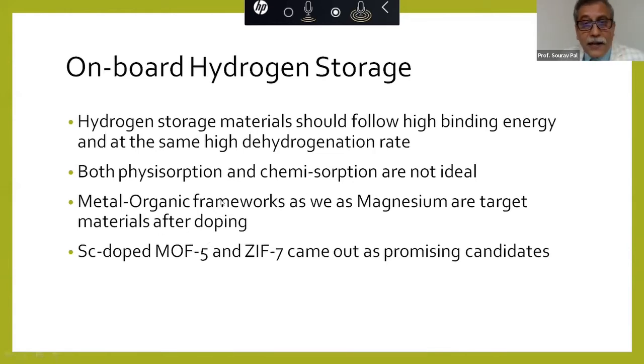So we have looked at metal organic framework, which is a physisorption material. We have looked at magnesium, which chemisorbs hydrogen well. And we have looked at what is the best thing. And among the many works that we have done, I can only say, because of lack of time, the most promising candidate is a scandium doped MOF 5. Of course, there are many MOFs, so one can even get various other materials, but the MOF 5 is what we have studied, along with ZIF.